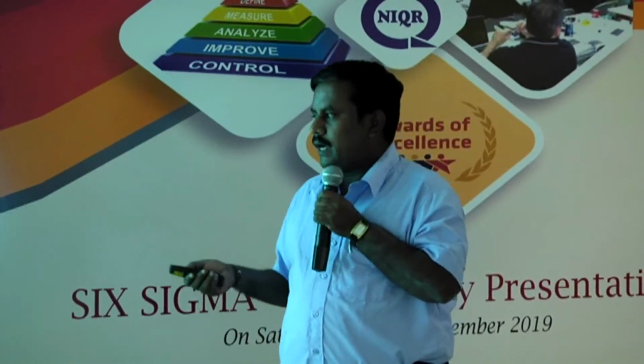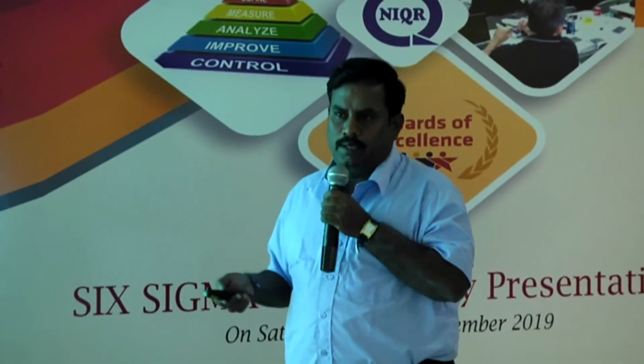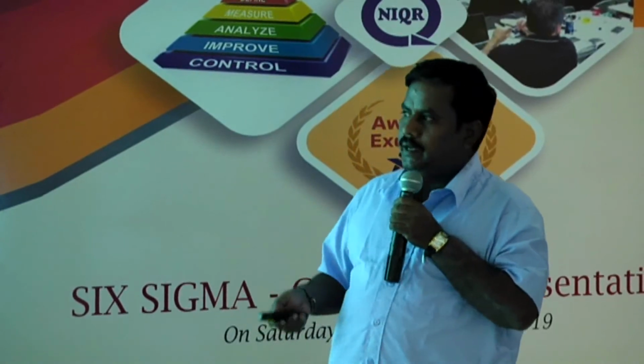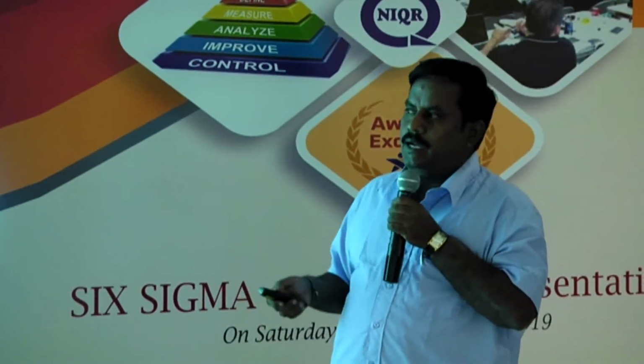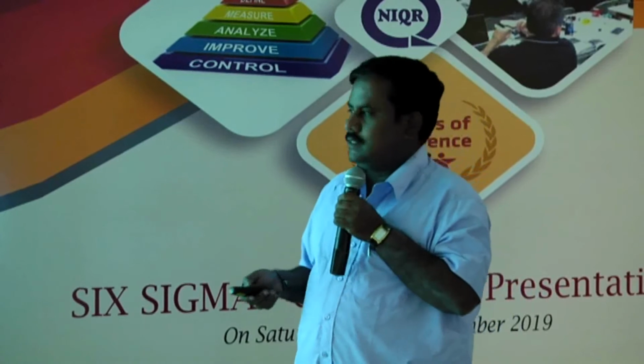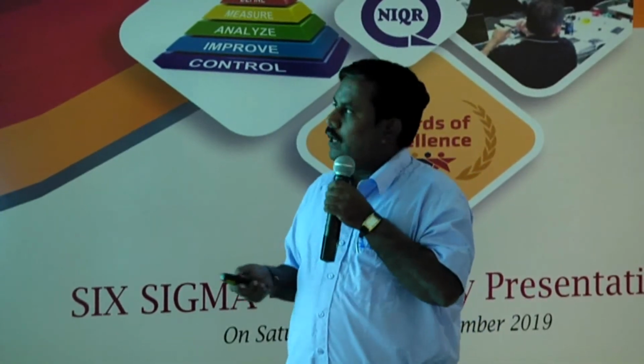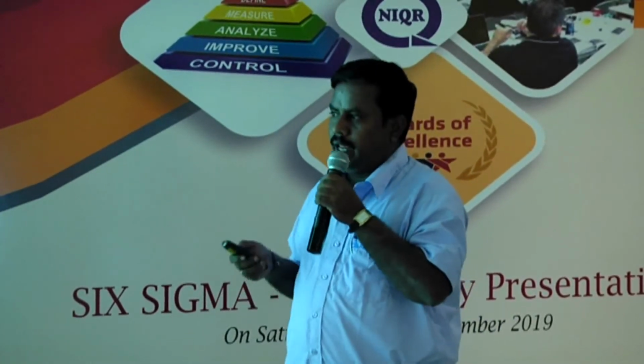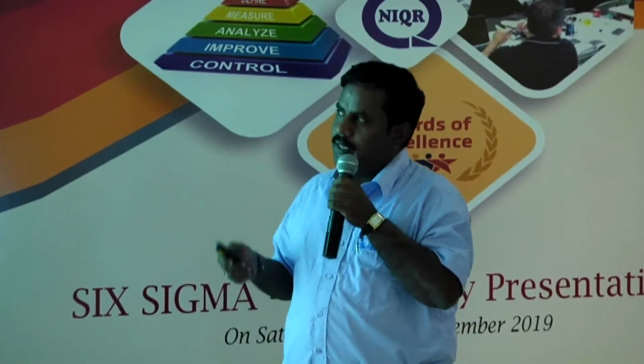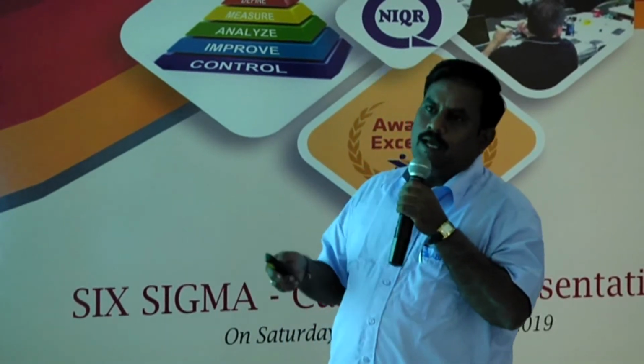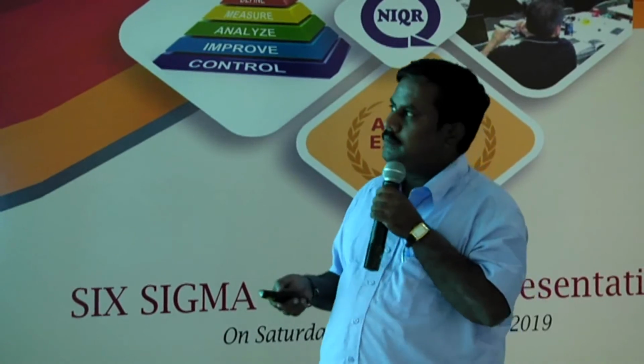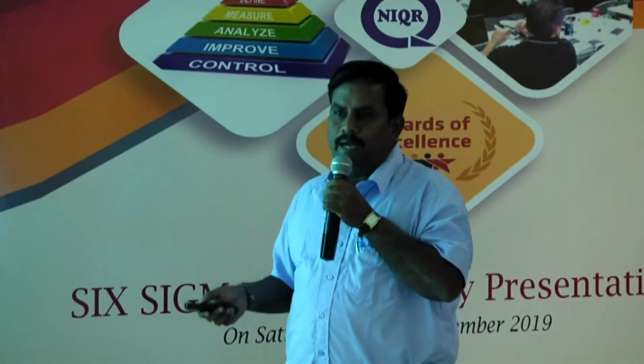Response details are collected after machining for the whole lot. It's a data collection sheet. Entire 3 shift data collected, with castings identified with numbers. A total of 8 best castings and 8 worst castings were collected, and then subsequently we collected the respective process parameters. We used the paired comparison tool.